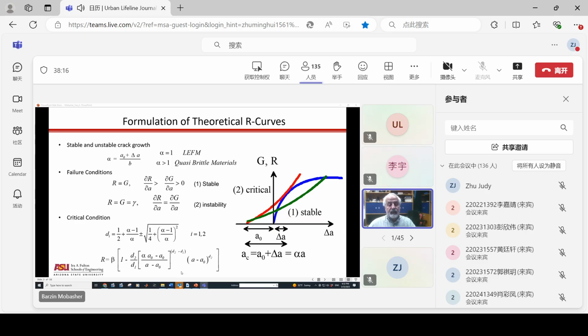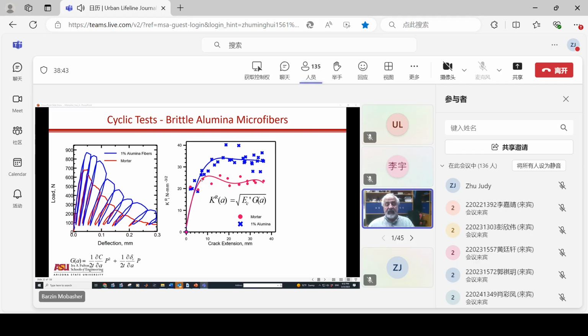And the solution that we gave was actually a solution to a differential equation. And the parameters are two parameters. One of them is a parameter alpha A, which is the amount of growth of the crack from the initial notch. And the second parameter is the toughness of the material that we can define as parameter beta. So with a two-parameter model, we can actually predict how much a crack grows and how much extra benefit we get. And this method has been used to show the toughness increase when you put fibers into concrete. And this is done by means of compliance calibration, which is a standard procedure now for measuring.